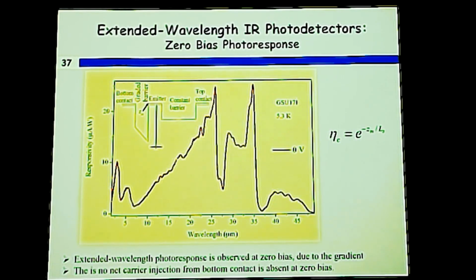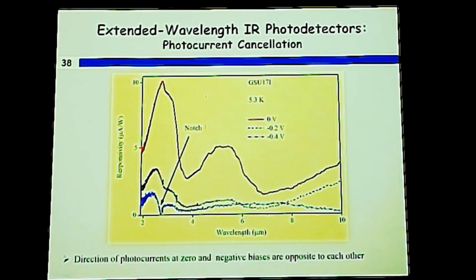And if you remember, when the filter was used to block the high energy light, the extended wavelength disappeared. So that is probably related to the blocking of the transition to this level, so that the extended wavelength disappeared. At zero bias we saw this result, and the directional preference also becomes clear when we apply small negative biases. With small negative bias, the photoresponse is in the opposite direction, so there is cancellation, and that becomes weaker now. With further increase in negative bias, at this wavelength it is completely cancelled. And in this range now, the photoresponse becomes stronger in the opposite direction. That's why we see the change in shape at 0 volt and at negative 0.2 volt. The shape appears to be similar, meaning that the current towards the bottom contact was dominant. Now the photocurrent is dominant in the opposite direction.